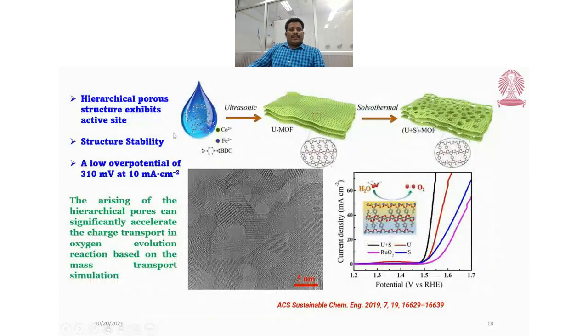Then another interesting report. These hierarchical structures are unstable in the presence of water and other organic solvents. So to overcome this, the existing MOF was prepared with two different synthesis methods. First, they synthesized with the ultrasonic method. It gives a sheet-like MOF. Further, they adapted it with the solvothermal method. It gives porous structures. The unstable moiety was removed.